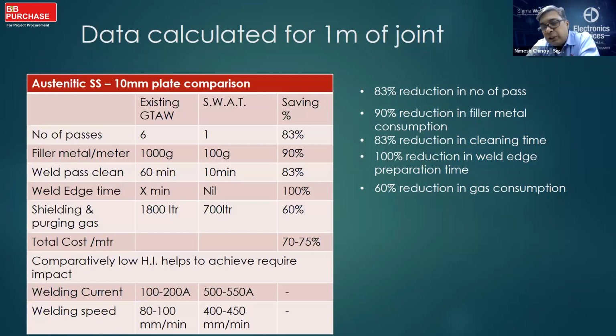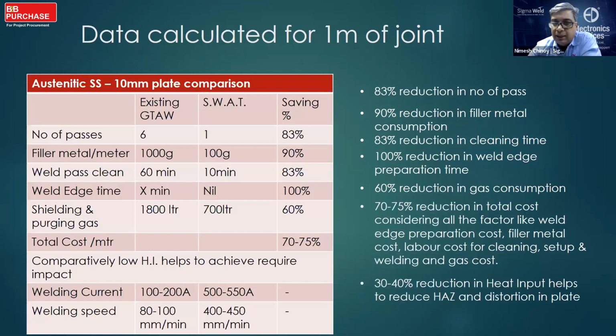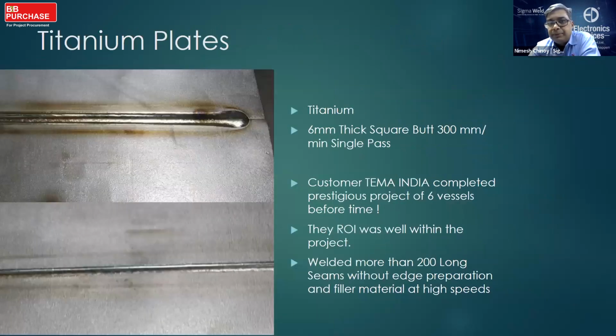And weld edge preparation, you save 100% of the time. Shielding gas, you would save about 60%. Total cost per meter, you would save 70 to 75%. In addition to that, you would save 30 to 40% reduction in heat input, which helps you reduce the heat affected zone and distortion on the plate.